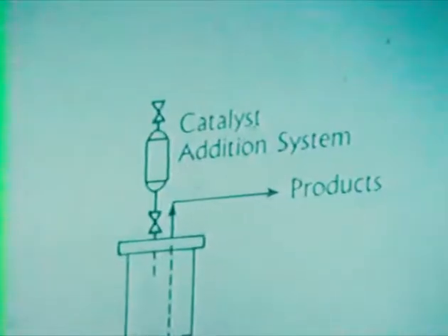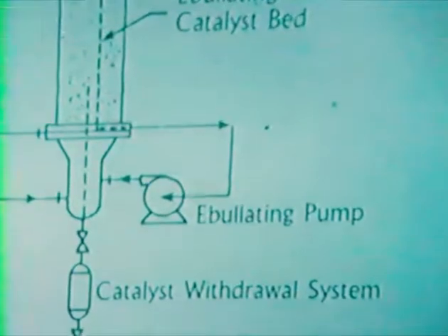shown here. Approximately 200 pounds of catalyst are loaded into each of these reactors, and in this particular run, both reactors were running in catalytic mode with the same catalyst, the Amocat. For the initial period of the run, the reactors were in batch deactivation mode, such that the only catalyst that was removed at a given time was a small amount, about a pound, for sampling purposes out of the 200 pounds, and then that equivalent amount of catalyst was added to maintain a constant bed.